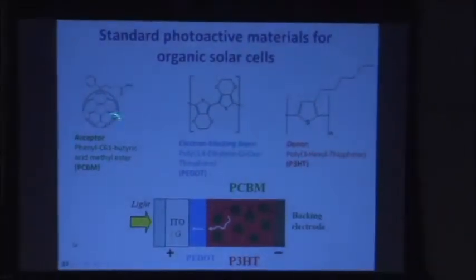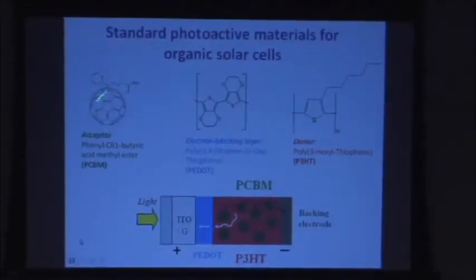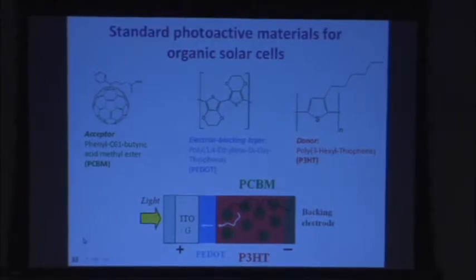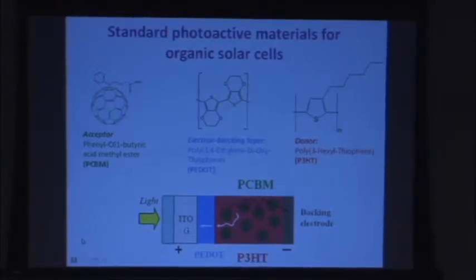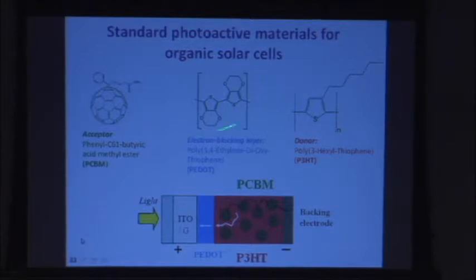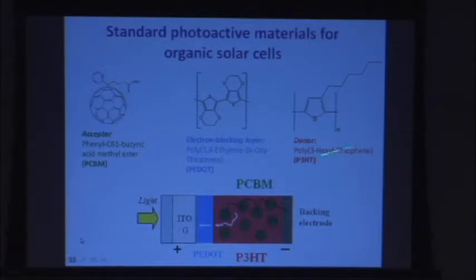With the standard solar cells we tested for compatibility are organic solar cells. Typically, organic solar cells are made by an acceptor that is fullerene or a soluble derivative of fullerene like PCBM that can be dispersed in organic solvents. You need a donor that is typically a conducting polymer. Very popular choice is poly(3-hexylthiophene) of the regioregular form that stacks and gives a good mobility. And this is a typical donor material.